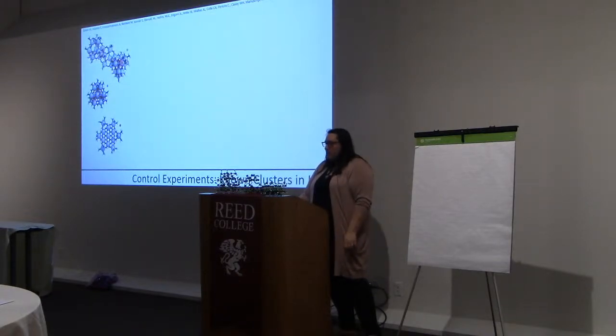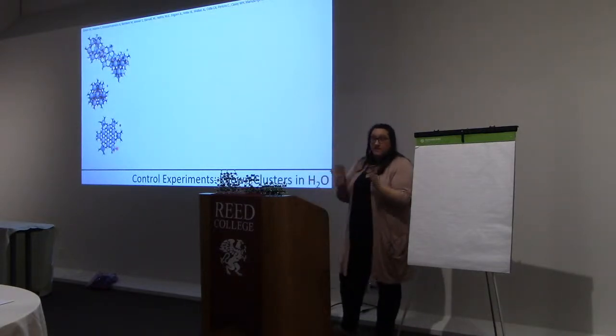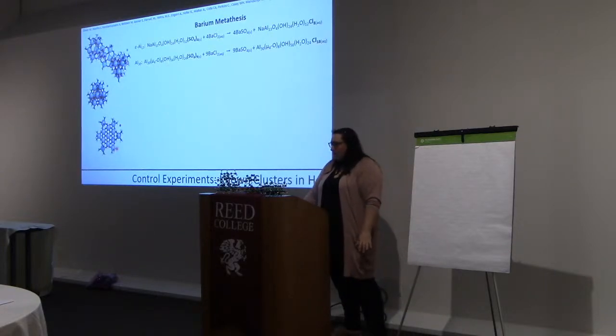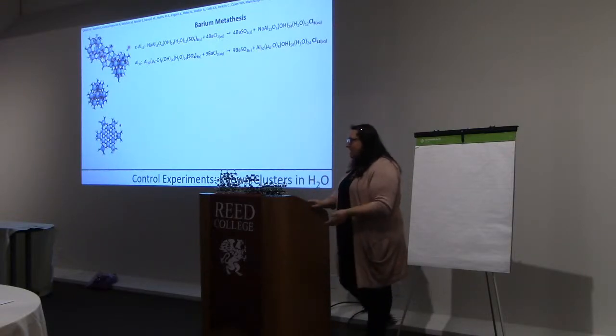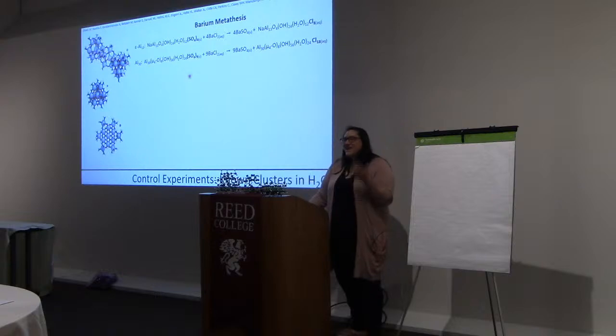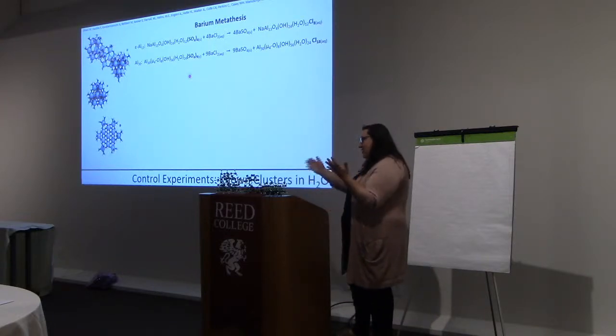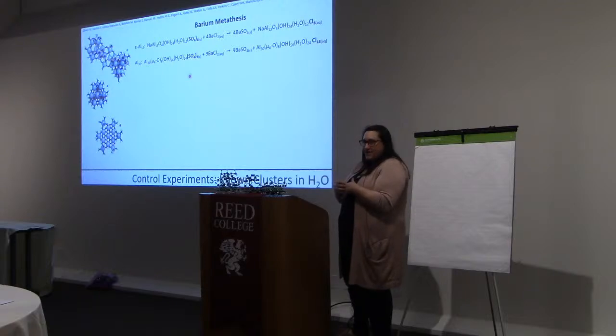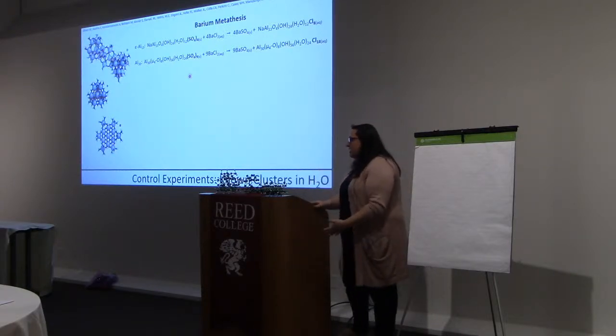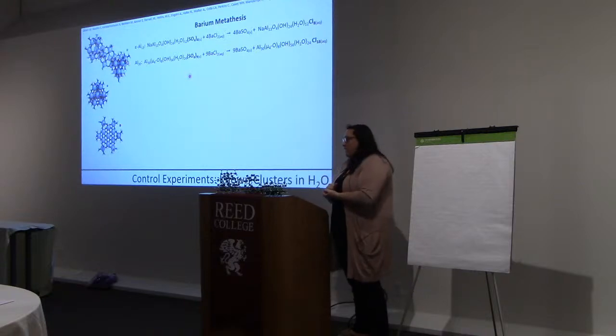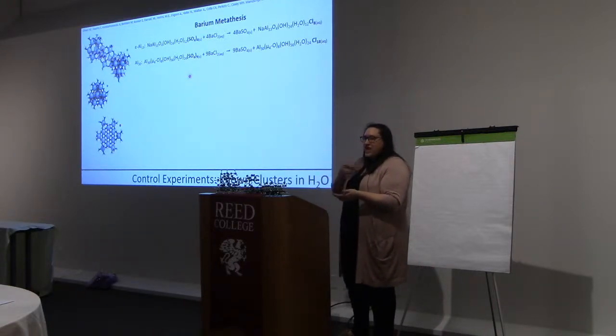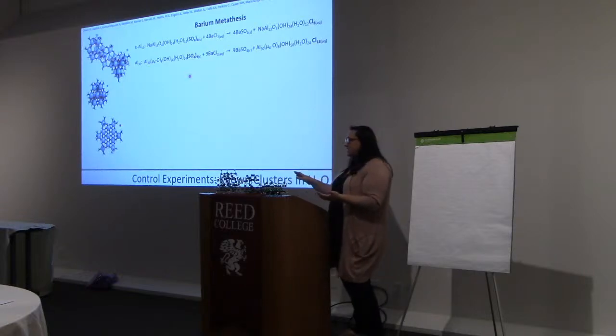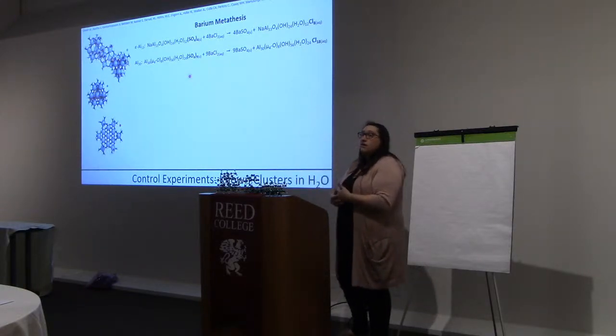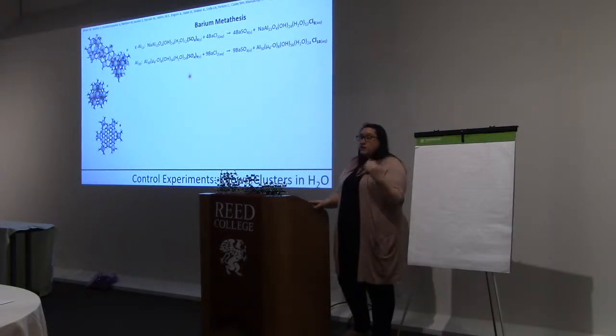All right, so these were the 3 clusters that my students and I were capable of synthesizing so far. And we were able to take these 2, and as I told you, when we crystallized them, they had sulfate counterions. They're not soluble with sulfate counterions, that's how we crystallize them out. And so we had to do a barium metathesis, a double displacement reaction, where we grind the powder up with barium chloride, and then we put it in water and shake it, and the barium sulfate stays insoluble, but any of the clusters that are then closer to chlorides dissolve, and you can get 100% of your cluster to dissolve using this method.